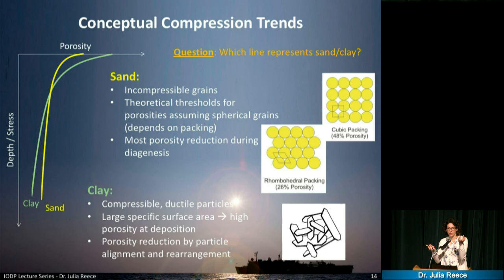So that means out of a volume of sediment, 70% or 80% is water out of the whole volume. And that then decreases pretty significantly with depth as you bury it, and all these particles start to rearrange and move past each other and align perpendicular to the applied stress, which is mostly the vertical stress. And so that's why we really get a very different behavior for a clay compared to a sand. And this is important for what I'm studying.